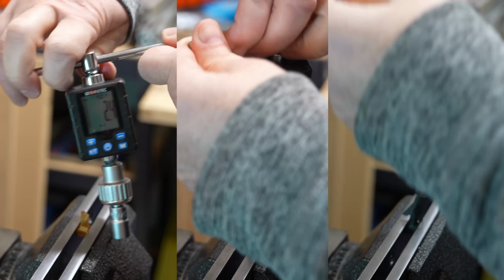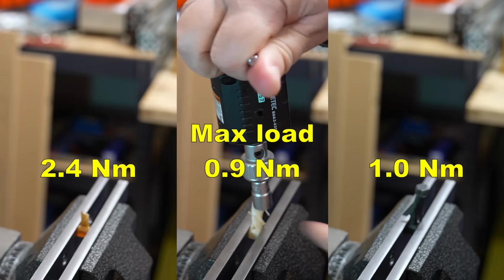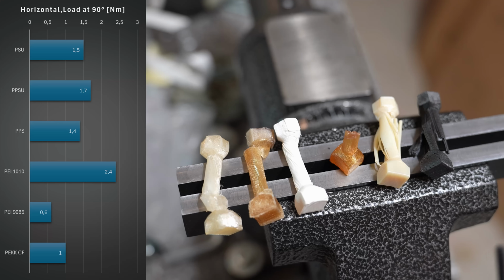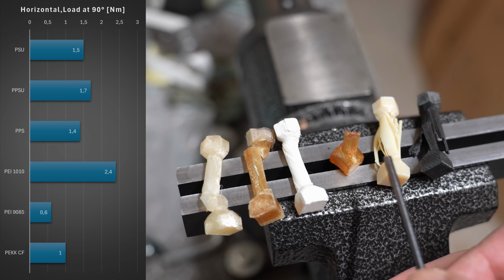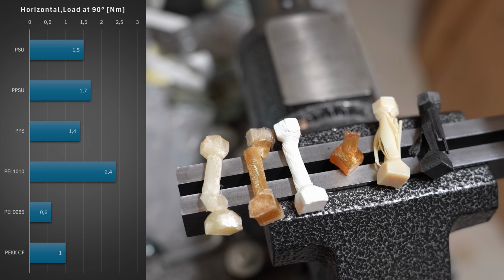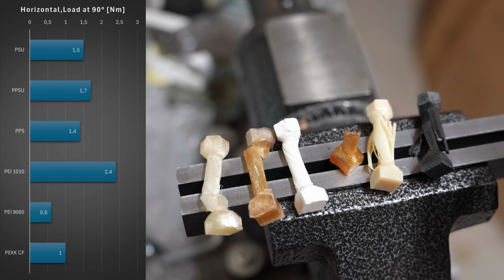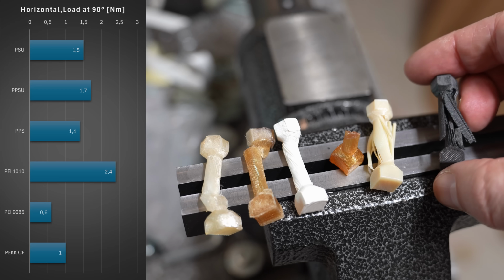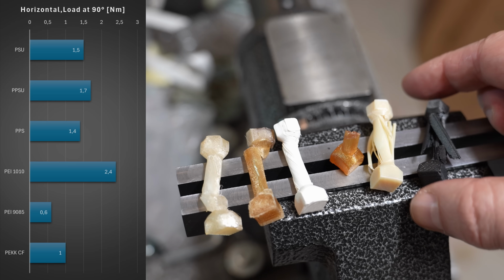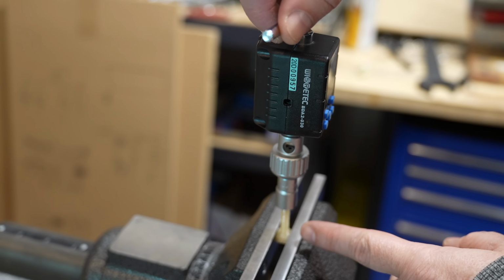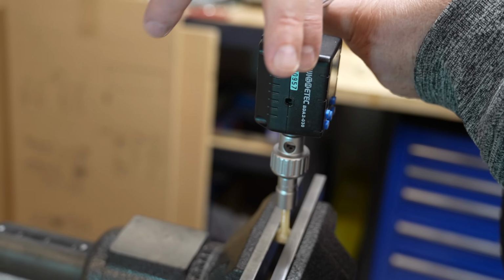2.4. Interesting situation we have here, especially with the last three. This breaks very suddenly. This has a weak layer adhesion, it delaminated between the layers, and the carbon fiber version of the PEKK breaks too early. And now vertically printed test objects where the layer adhesion is important.